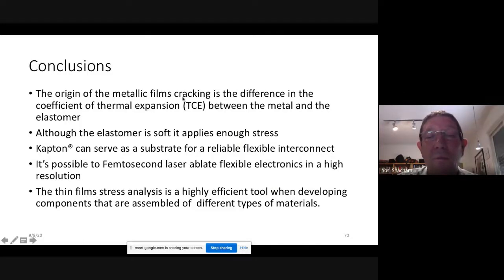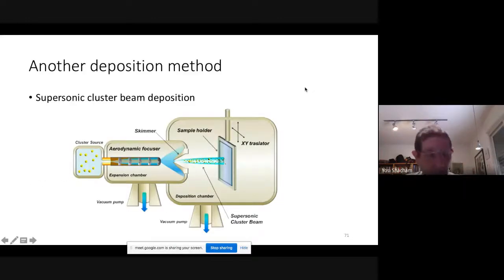And the origin of the metal film cracking is the difference in the coefficient of thermal expansion. And also the elastomer is soft, it applies enough stress, and Kapton can serve as a substrate for flexible interconnects. And a combination can be a Kapton substrate, and then on top of it, PDMS and then metal. And femtosecond laser ablation is a good technology. And thin film stress analysis is a very efficient tool when developing components that are assembled of different types of materials. The last topic I want to talk about today is a very new technology, which is extremely, I think